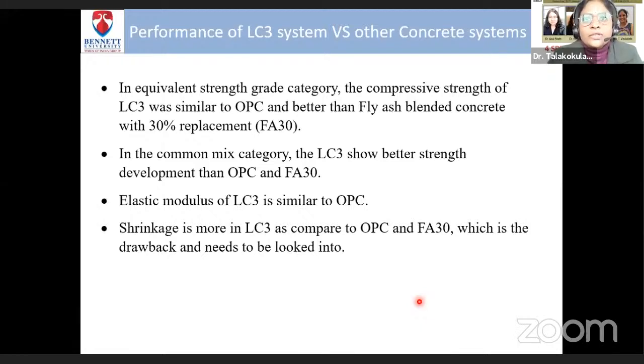If you look into the compressive strength, which is very important for any concrete, in the equivalent strength grade category the compressive strength of LC3 is similar to that of OPC and better than the fly ash blended concrete with 30% replacement. In the common mix category, LC3 shows better strength development than the OPC and the FA30. Elastic modulus is very similar to OPC. The shrinkage is a bit more in LC3 as compared to OPC and FA30, which is a drawback, and studies are going on on how to rectify this, which is being looked into by the researchers.